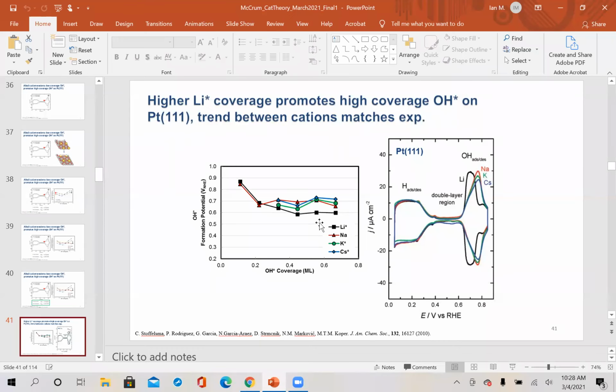I should say when they come to the surface, they're not fully desolvated. They lose some portion of their solvation, we expect. And so yes, certainly the solvation energy plays a role. The issue is with the cations we've looked at so far, the trend in cation size tracks with the trend in solvation energy. Because for the cation in bulk solution, at least the alkali metal cations, their size is what dictates their solvation energy, right? If they're tinier for the same charge, they interact more strongly with solvent. Yeah, and that's true.